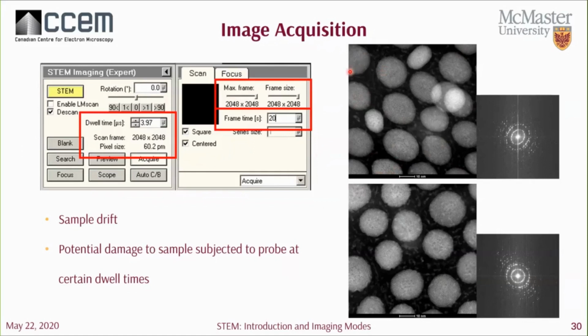So the most apparent artifact that you could see in your image is sample drift. This is just an example. I can be a little impatient sometimes. You don't let the sample settle on the microscope and you try to acquire an image. This is what you actually get. You can see that the stage or your sample was drifting in this direction, and you can see that in your FFT. Note that the stretching is not from astigmatism, but from sample drift.